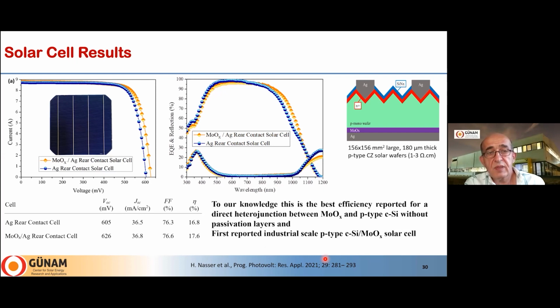Very recently we published this paper in Progress in Photovoltaics. You see the solar cell results comparing two cell structures, one with molybdenum oxide and the other without. Here you see the external quantum efficiency profiles, and the advantage of using molybdenum oxide on the backside is clearly seen from this external quantum efficiency plot. These yellow, orange dots show the molybdenum oxide results, and they are higher, giving higher current values than the reference sample.